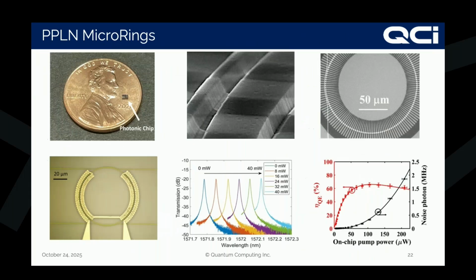And we can also make PPLN in microring formats. As you can see in here, the SEM images in the middle show a poled device, and that's why you see the differences in color, because it showed differently on the SEM. We can make microrings and thermally control them very accurately. On the bottom row, that's what you see in the microring format. With from 0 milliwatt to 40 milliwatts of thermal power applied, you can shift the resonance wavelength of the microring and effectively build a filter from that.